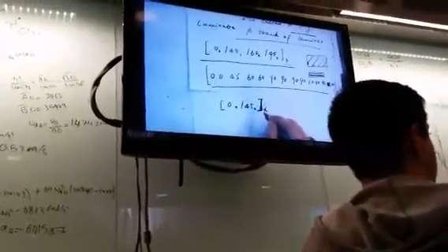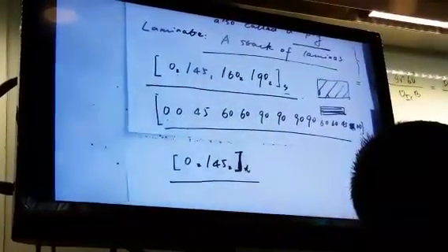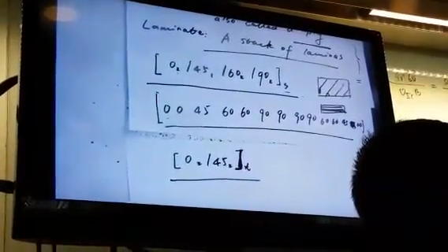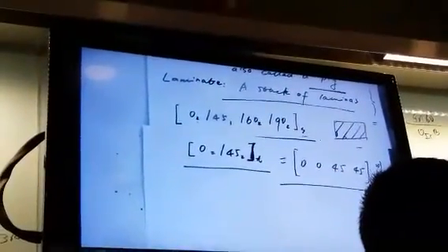And sometimes we have another different one. 0, 2, 45, 2, T. What is the meaning of this one? T means total. It's the total number of plies. Okay? This one is the same in meaning. There are no symmetry layers. This T means total layers, so 4 layers. This is the composites model you should build for this notation.